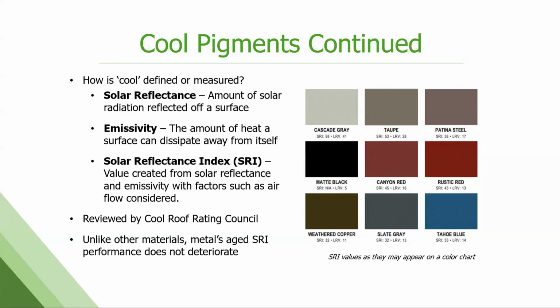And that's one advantage pre-painted metal has. The SRI values for pre-painted metal tend to not move at all over time, and sometimes they actually improve, because we just have hardly any fade or color change over time. Got an example here of what a color palette, color chart might look like from panel manufacturers these days. They almost always list their SRI value or their solar reflectance value on those colors now. And obviously, matte black, not made with cool pigmentation, is still problematic, but you can get a black that qualifies as cool, depending on your definition. That is possible.